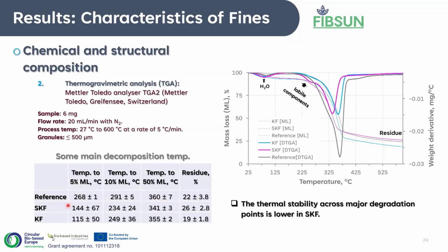compared to the hemp. But we notice that in the case of the SKF and KF, with the super short and short fibers, there are slight variations in thermal stability, but nothing notable. The only notable increase in thermal stability was achieved at the 50% mass loss, which again shows that KF is slightly more thermally stable than SKF, which corroborates the chemical composition of the material.